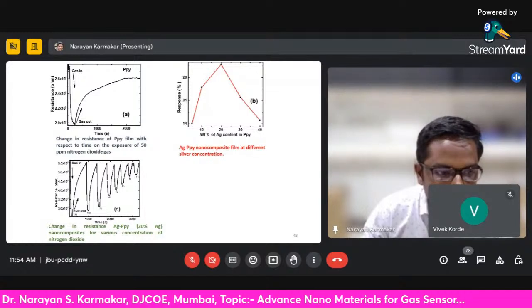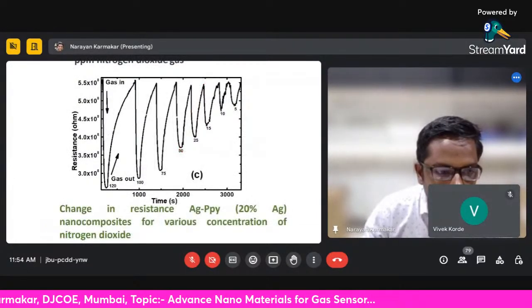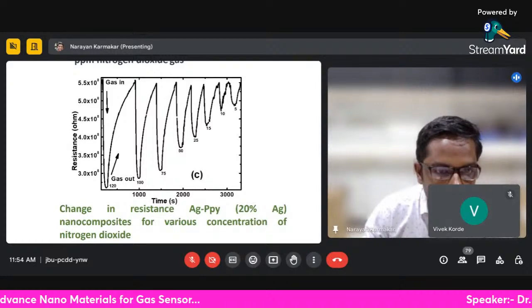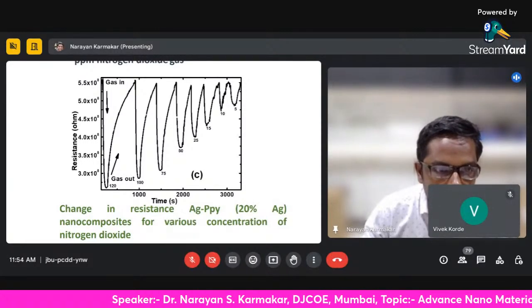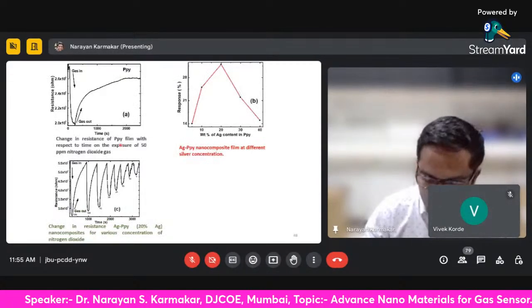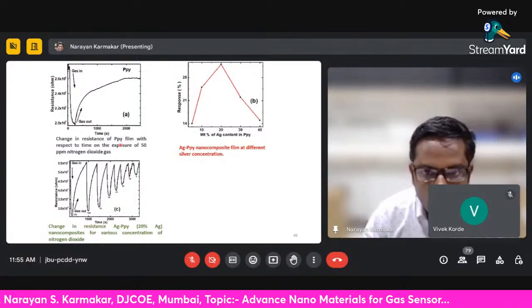Then we studied the variation of concentration of AgPPy for 20% Ag. We saw that the sensor was able to detect 5 ppm gas, as well as detect about 120 ppm gas with overall good sensitivity. We can see the resistance was decreasing.